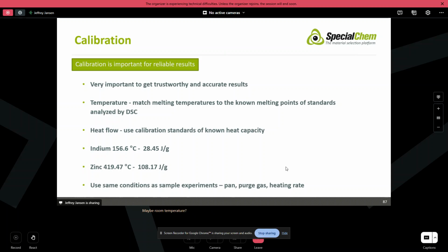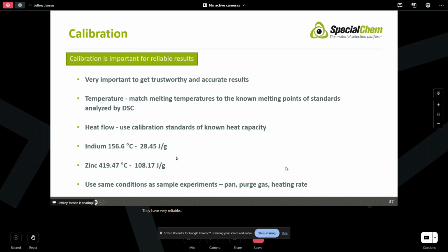Maybe room temperature. So you leave the pan open, you have a calibrated thermometer in the laboratory, and you use that. Then you use indium, which has a very set melting point, and use zinc, again, very set melting point, pure samples. And you can, again, create a calibration curve for temperature. You also want to use heat flow, and again, you can use those same metals. They have very reliable melting point or heat of fusion, and you can look at that. So again, both those calibrations.